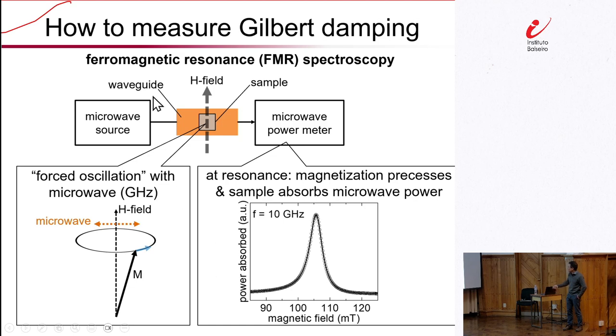So whenever the magnetic material reaches resonance, in other words, the magnetization is precessing at its maximum cone angle, it's absorbing the maximum amount of the incident microwave power. So by keeping track of how much of the microwave energy is being absorbed, you see this peak, which corresponds to the resonance condition. So the magnetization has a combination of favorite frequency and externally applied magnetic field at which it wants to precess.